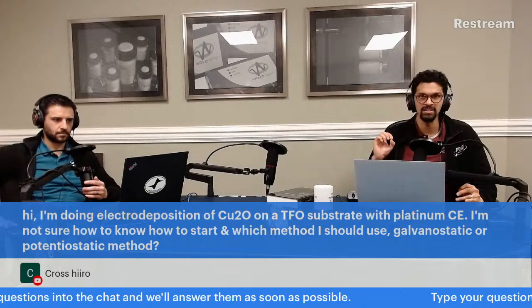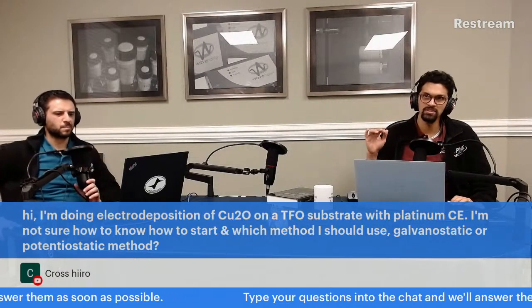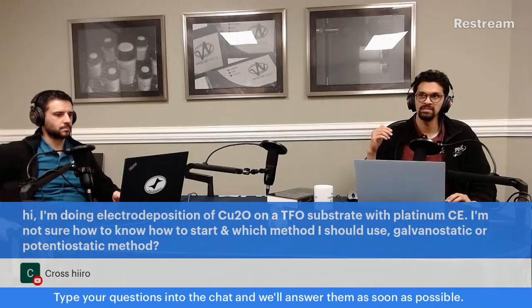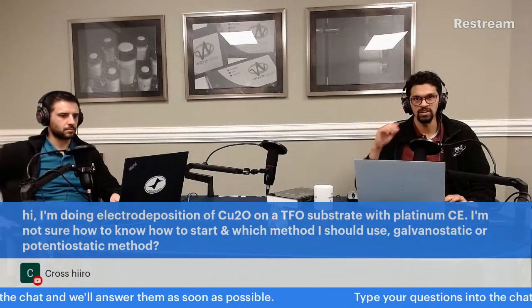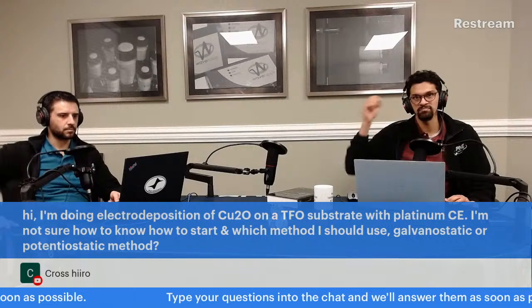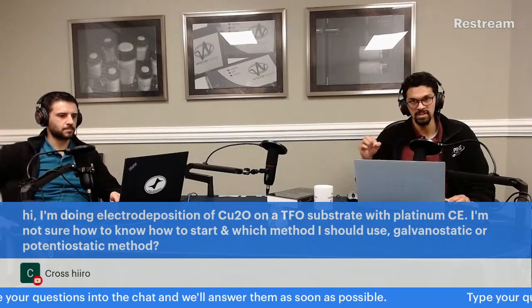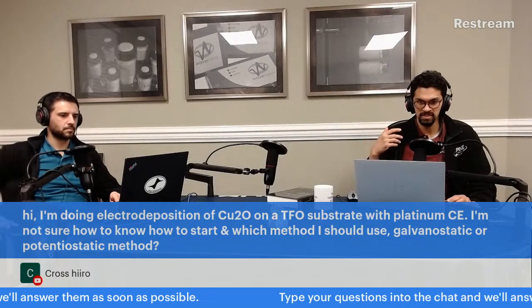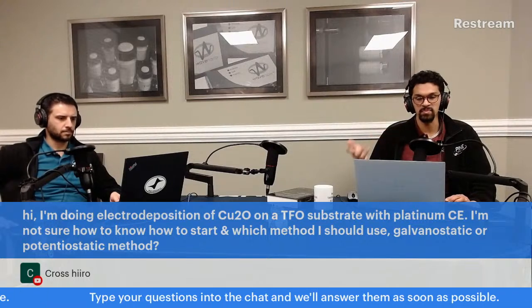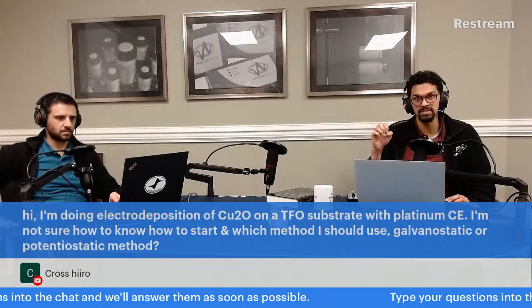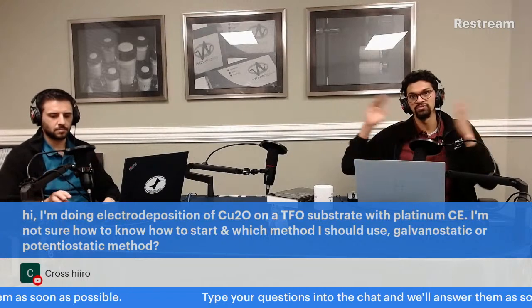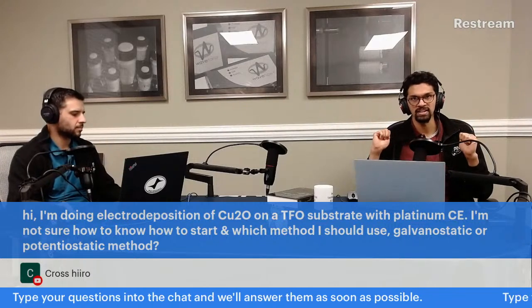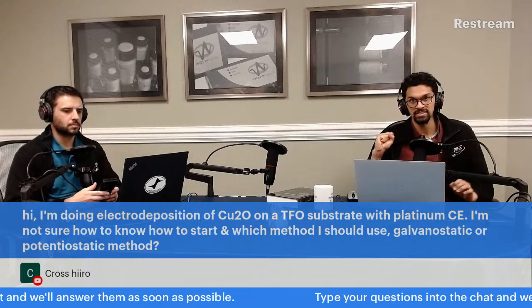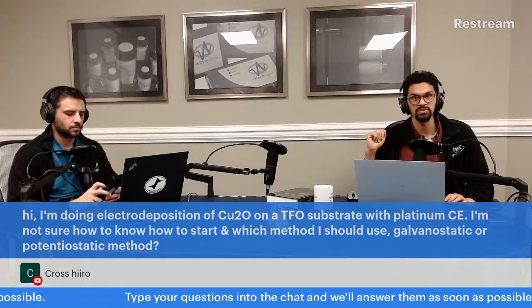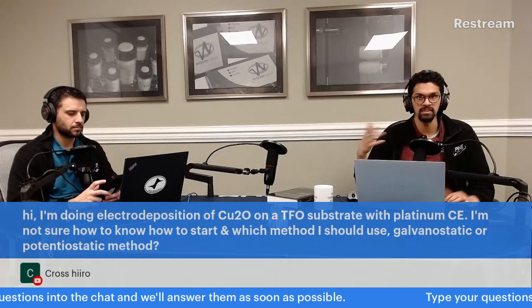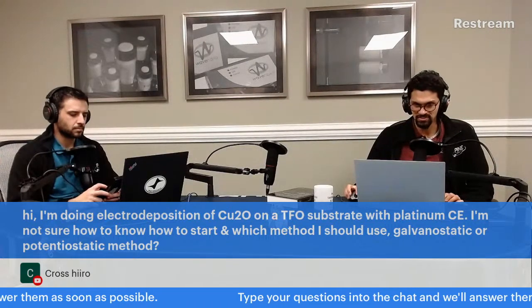You start potentiostatically, and once you understand where the potential is, then you can start doing galvanostatic experiments and try to adjust the rate and make sure that the potential you're measuring in a galvanostatic experiment is near the potential of, I'm assuming the electrodeposition is a reduction reaction of copper oxide on FTO. So then you can see where that peak is, what that potential is, and galvanostatically you can verify that the potential you're measuring is at that potential. And during your galvanostatic experiment, if you notice the potential moving around, you know it's no longer doing that deposition, and then you can turn it off and evaluate your system. So that's my recommendation.